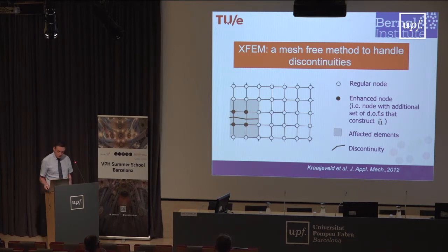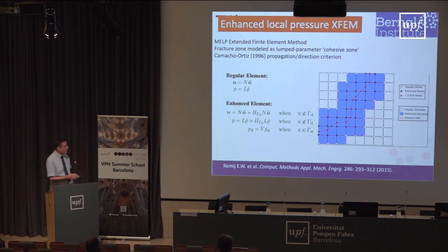As you propagate through the mesh, you progressively enrich nodes as you go through the finite element analysis. And so at some point you get a whole path followed by the finite element method and progressive enrichment of all the nodes which are tainted in black here. What you basically do is use the same thing as regular finite elements, using displacement degrees of freedom and pressure degrees of freedom, but you enrich the displacement and you enrich the pressure by means of an extra discontinuous shape function.